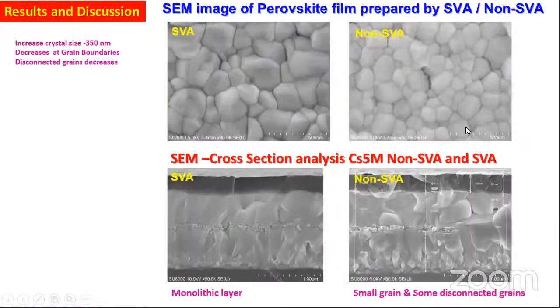This is a SEM image of the top surface of the perovskite film. The SVA annealed device shows larger crystal size compared with the non-SVA method. It has decreased grain boundaries compared with the non-SVA. Here we can see some disconnected grains, but in the case of SVA we cannot see this kind of disconnected grain.